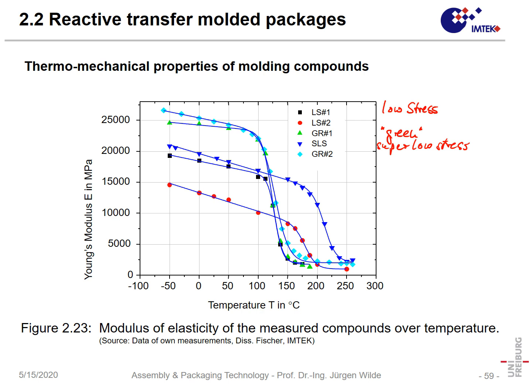And now let's have a look at the properties. Typically, the temperature range of application would be -40 to maybe 180 or so degrees centigrade. But on the other hand, it's often desirable to look at a somewhat larger temperature range, so we do not have to extrapolate our data. So, starting at low temperature, we have a certain Young's modulus, which is relatively high for a plastic material. The reason is that it's mostly a silicon oxide embedded in a little resin here.